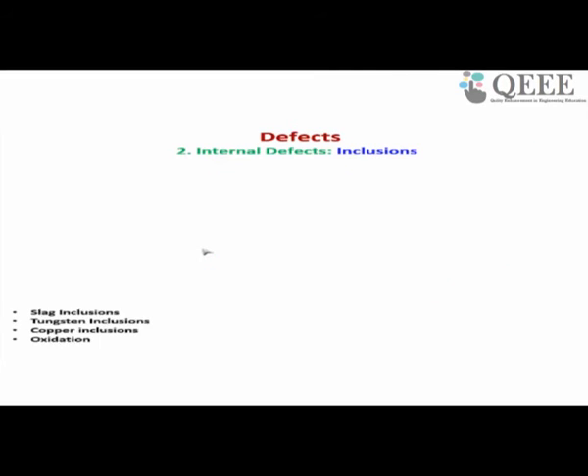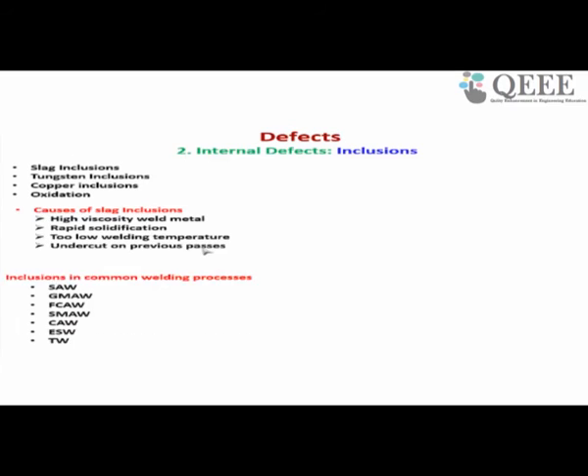Similarly, undercut. If there is undercut, the slag may be placed inside the undercut, so it may not be able to come out to the top surface. As a result, you will get slag inclusion. In almost all fusion welding processes, you get this kind of slag inclusion. Okay, so this one we discussed.